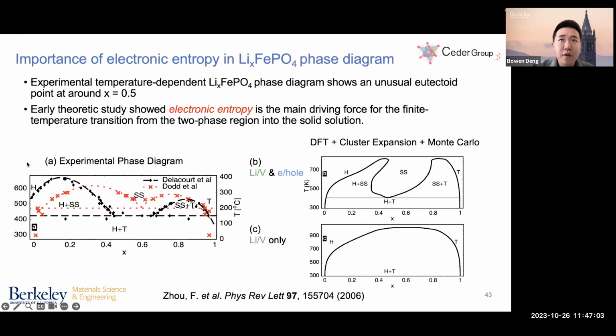And figure A on the left here shows a temperature-dependent experimental phase diagram of lithium iron phosphate, where the x-axis is the fraction of lithium and the y-axis is the temperature in Kelvin. And you can see at low temperature, the lithium removal goes through the miscibility gap between a high lithium and low lithium phase. And around 400 K, there is an unusual eutectoid transition into the solid solution phase around x equal to 0.5. And an early theoretical study shows that electronic entropy is the main driving force for this finite temperature transition from the two-phase region into the solid solution.